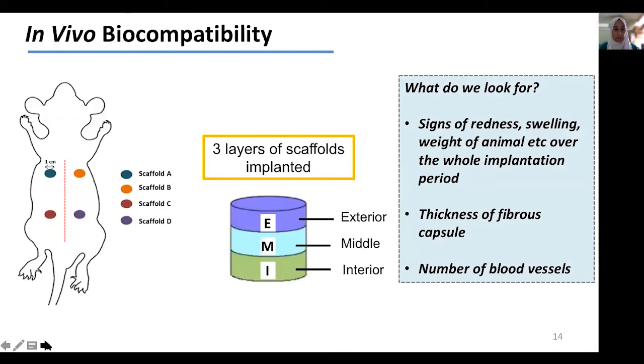Because the scaffolds that we are fabricating are intended for human applications, we have to ensure that these scaffolds are non-toxic and biocompatible. Therefore, we carried out in vivo biocompatibility studies where the scaffolds were implanted in Wistar rats. So basically what we do is that we create subcutaneous pockets on the dorsal region of the rats, and then we implant 3 layers of scaffolds in each subcutaneous pocket. The 3 layers of scaffolds were labeled as exterior, middle, and interior. The interior layer of the scaffold was the layer that was in contact with the muscle layer, and the exterior layer of scaffold was the layer that was in contact with the skin.